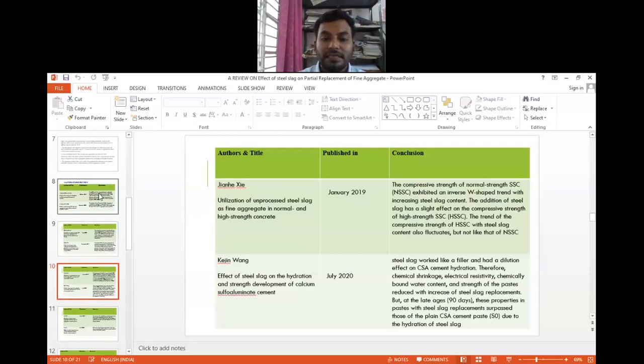The next researcher is Wang. Effect of steel slag on hydration and strength development of calcium sulfoaluminate cement, published in 2020. The steel slag worked like a filler and had a dilution effect on CSA cement hydration. Therefore, the chemical shrinkage, electrical resistivity, chemically bonded water content and strength of the paste reduce with the increase of steel slag replacement, but with the data at 90 days. He concluded with the 7 day, 14 day, 28 day and 90 day tests. The comparison of those properties is explained.